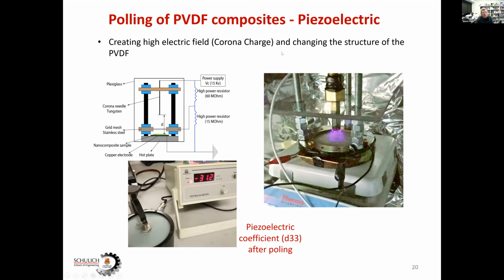And this is how we pole. Okay, we apply high voltage. And this is homemade; my students have made these meters, and then we apply extremely high voltage, in this particular case about 15 kilovolts. And when we apply this high voltage, those fluoride chains can be aligned, okay, through poling, and we can achieve a fairly high piezoelectric coefficient. This is a 31.2 for this film, and we can use these as a sensor.